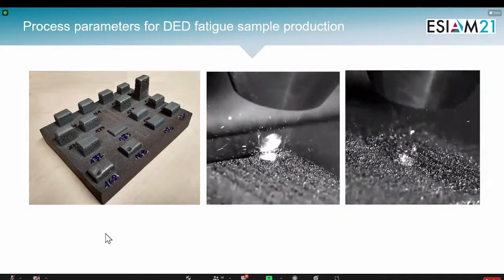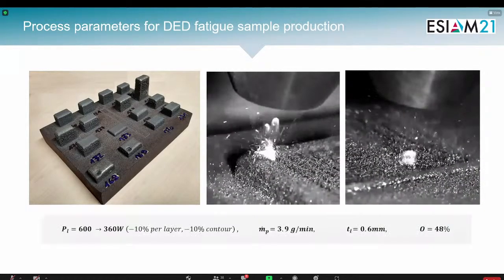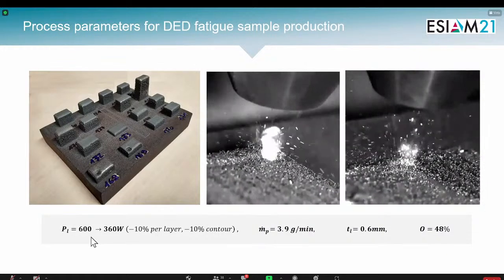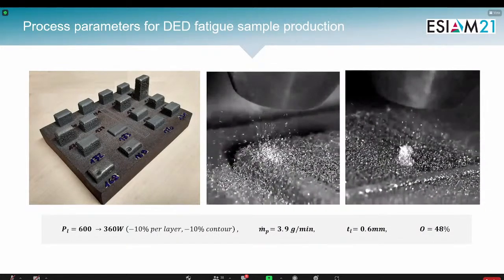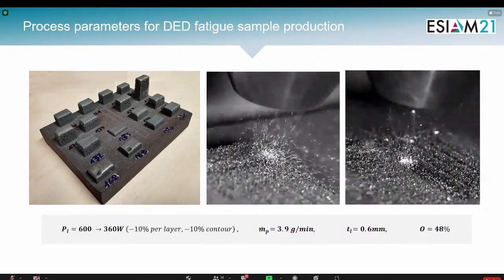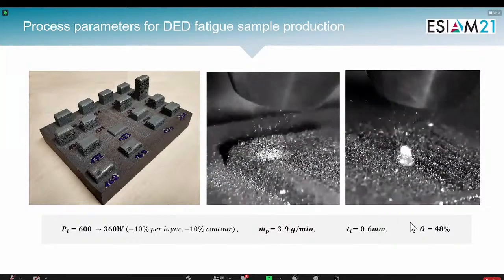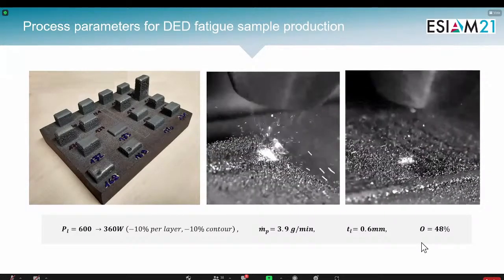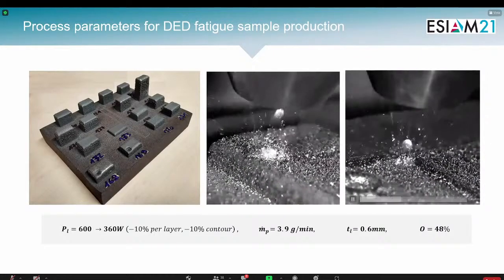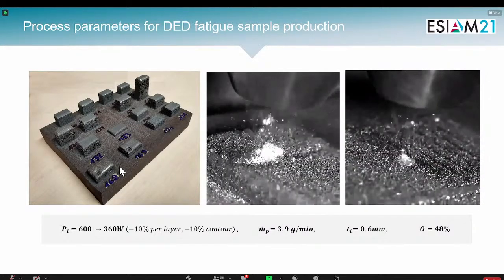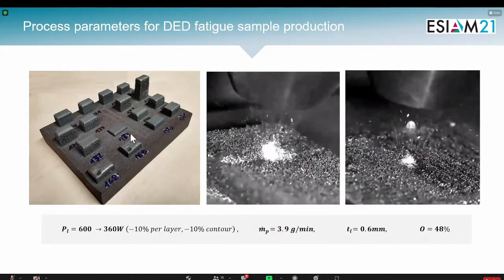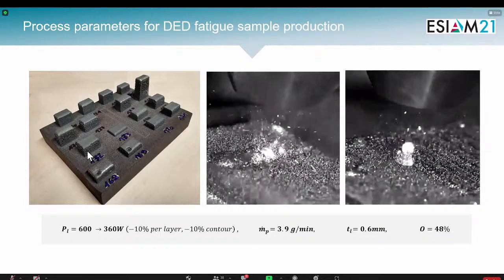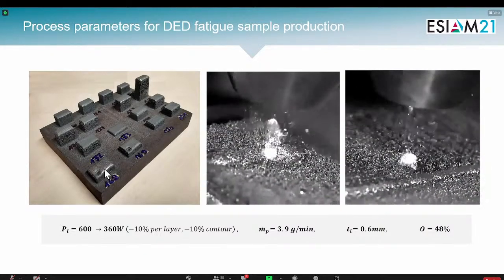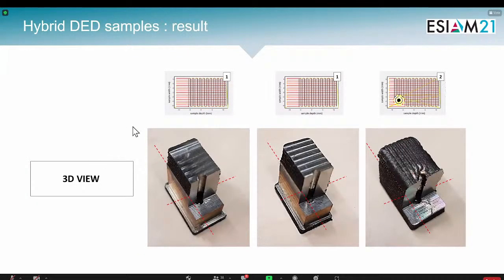Now, for the study, 30 samples were printed in order to obtain the highest geometrical accuracy, and the laser power was controlled on the contour of the sample and on the contour of the capillary with respect to the infill. And it was observed that the laser power, the mass flow rates, the layer thickness, and the overlap are closely related parameters and need to be tuned in order to get a good geometrical accuracy. On this figure, you can see full samples where we will drill afterwards. Here, the capillary is directly considered in the printing trajectory. These are the results, just to give you an idea of such samples where this part was milled and this part was not milled yet.